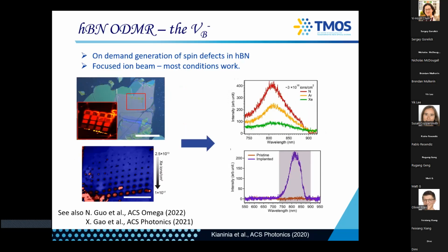So this is our earlier attempt with just xenon. But more recently, you can do it with argon, nitrogen, or any focused ion beam that you have. You have many of those around here. You can create beautiful arrays on basically any exfoliated flake. So this is pristine versus implanted. Again, no annealing needed because it's just a vacancy. If you anneal, they will diffuse out and the emission will disappear.